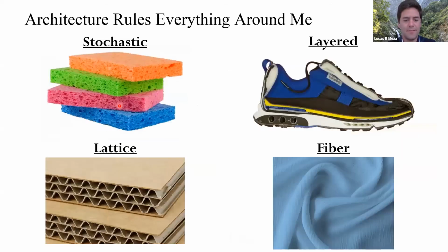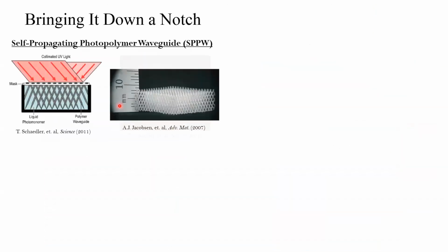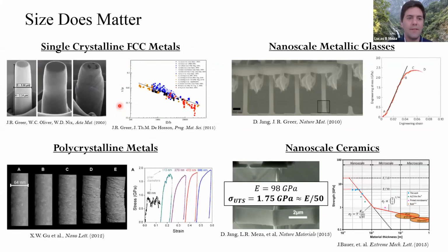You said that was for FCC metals - is that true generally or only for those cases, and do we know why? In general, this happens for different types of materials - FCC, BCC, HCP generally holds. I think that size effect is more pronounced in FCC than other materials. Part of the problem is HCP hasn't been studied as much because it's weird and complicated, and Julia's group had been getting into that when I was leaving. But when you have prismatic slip versus basal slip, it really depends on what orientation your structure is in, and you get pretty drastic changes in strength because of that.